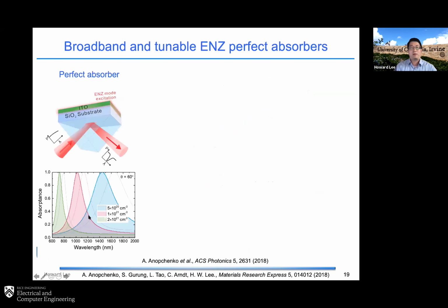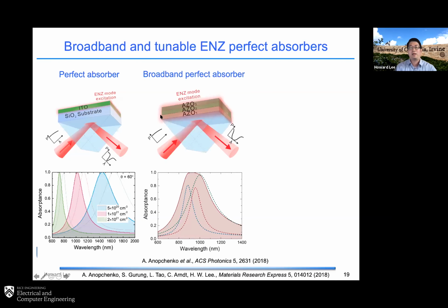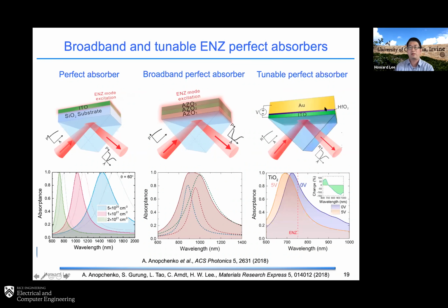So with this, we were able to demonstrate before, for example, making a thin film perfect absorber using the ENZ material I mentioned to you. At the same time, we are also able to, for example, stack a multilayer structure. Instead of one ENZ layer, we have three different ENZ layers with different ENZ wavelengths. That means each of the layers has a different carrier concentration. Then what you can have is a collective excitation of these ENZ modes. As a result, instead of one single absorption band, you can have a broadband absorption here. So you can really decide the layers and the ENZ wavelengths to make a broadband effect in this kind of ENZ structure.